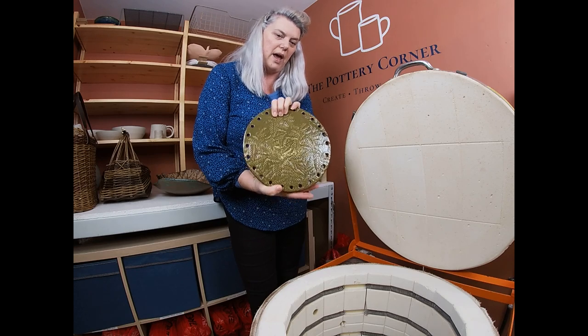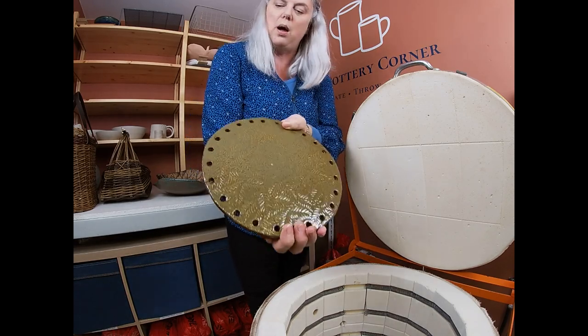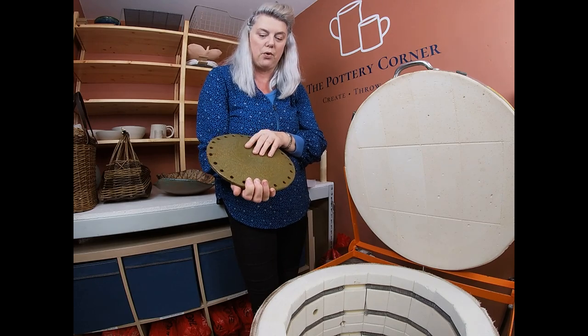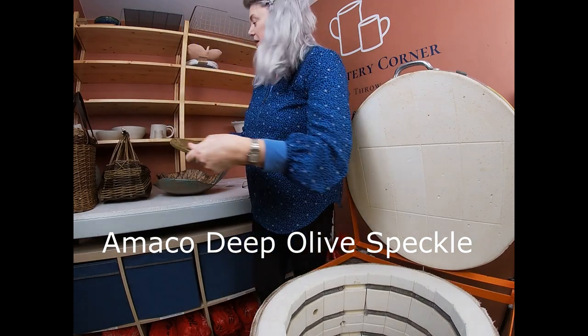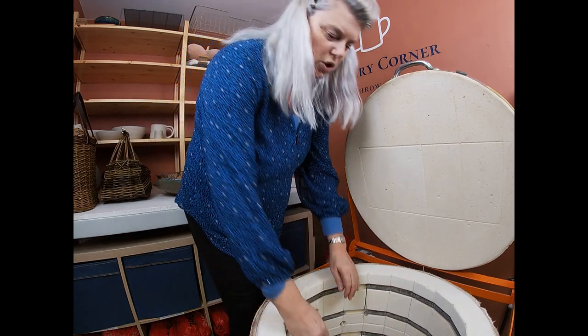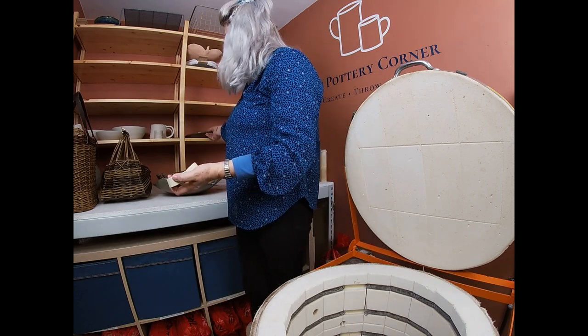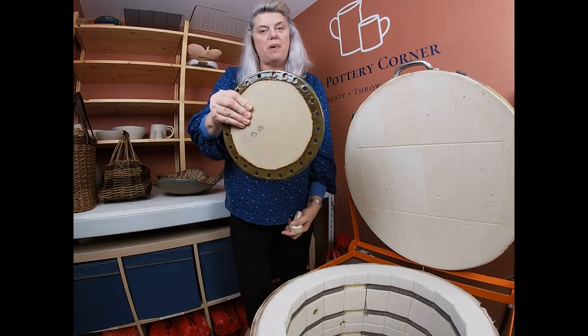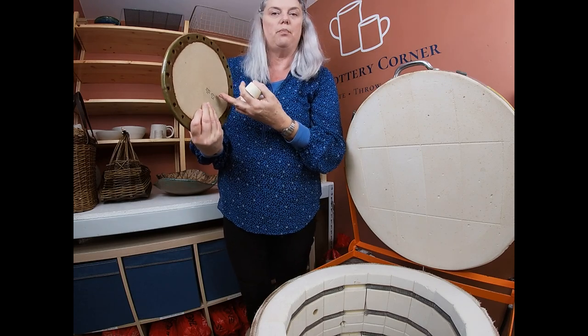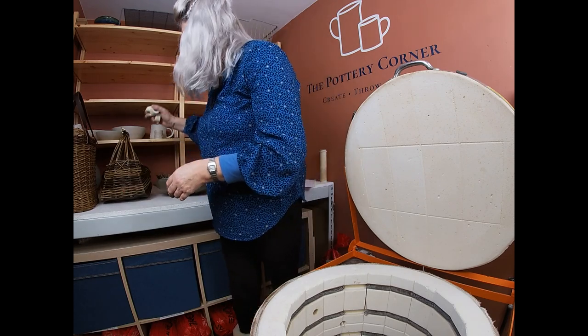We are asking the clay to do quite a lot there by making these holes quite near the edge. It's still a work in progress — that one has split, but we could use it as a prototype. The glaze on here is Amaco's Deep Olive Speckle. So that's a disappointing first one out. I have got more that I haven't yet glazed, so when I come to pop them in the kiln, I'm going to have to work out how to stilt them. This time I did it on kiln props because I wanted to have a glazed edge on the back so that when the willow went through it had the glazed section — but of course that means I can't put it flat in the kiln, and clearly it's asking a lot of the piece not to warp. So we'll have to do a little bit more thinking on that.